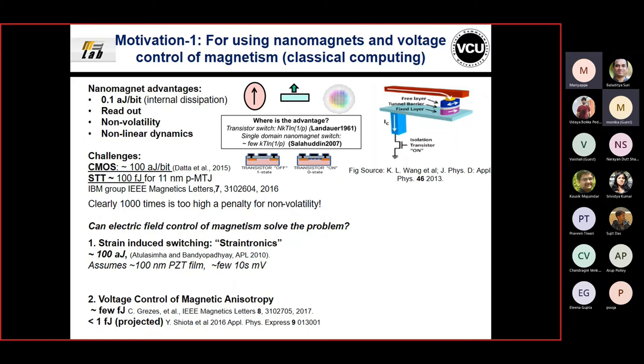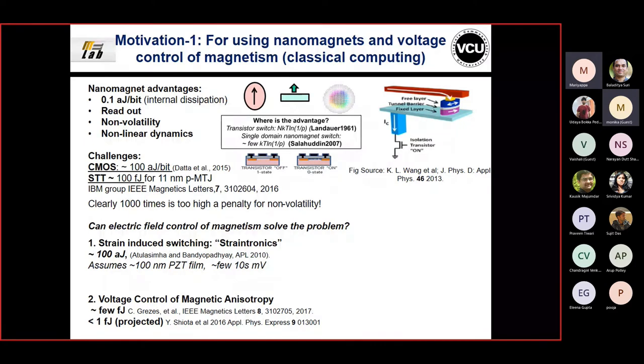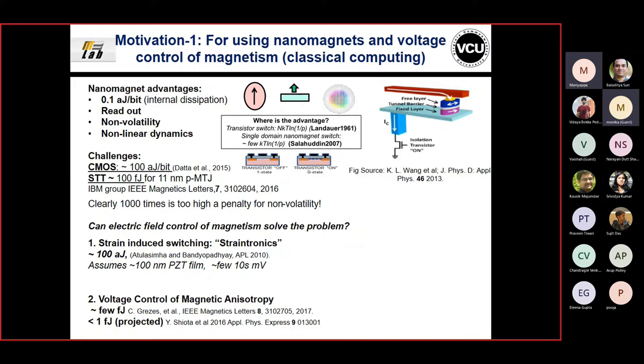However, right now N has been becoming less and less, and this will never be one kT because of incoherence in switching. So this is really not the argument for magnetic memory. But one thing that can never be taken away is non-volatility. If you have a CMOS device or transistor, you switch it off and the information is gone. Whereas in a magnet, that information is retained for centuries if the energy barrier between states is one electron volt or 40 kT. So there is a huge advantage where you can compute with this kind of memory.